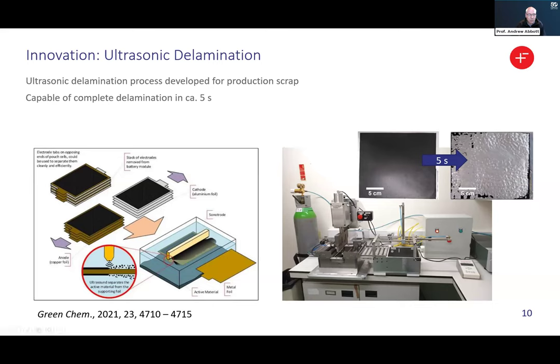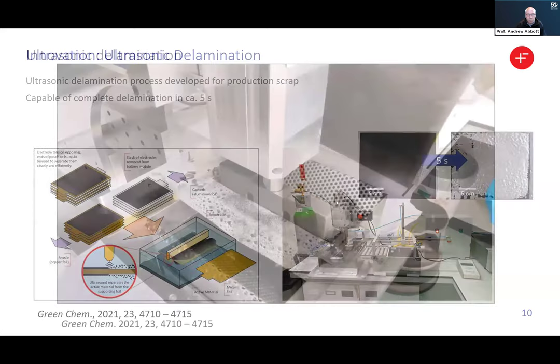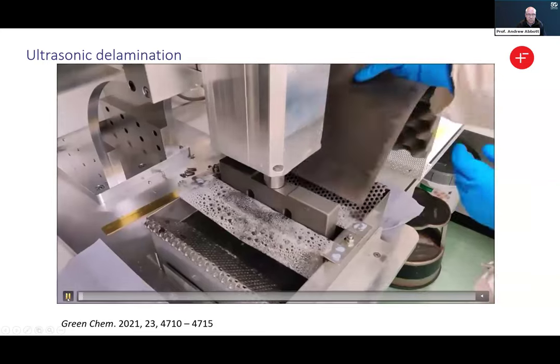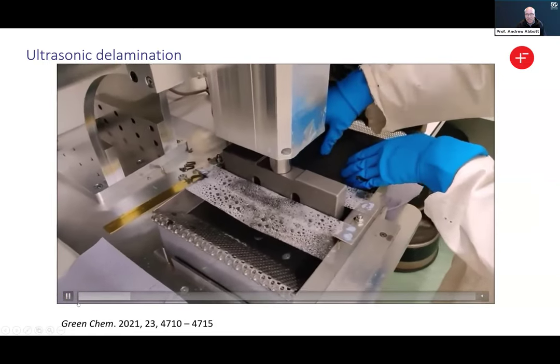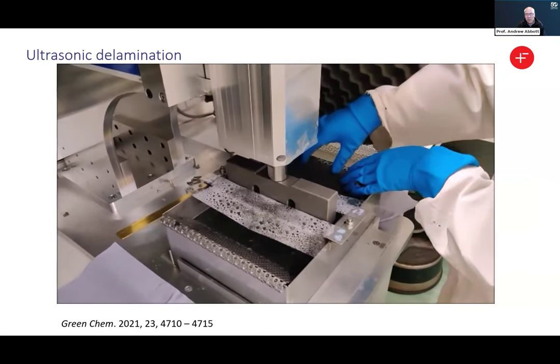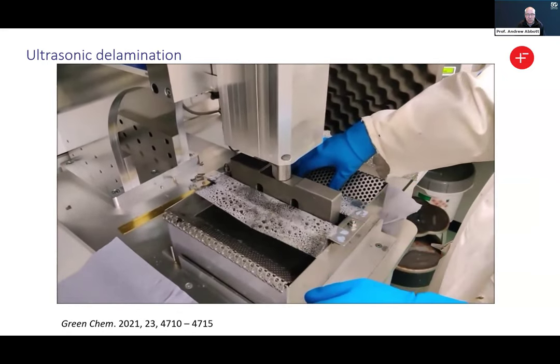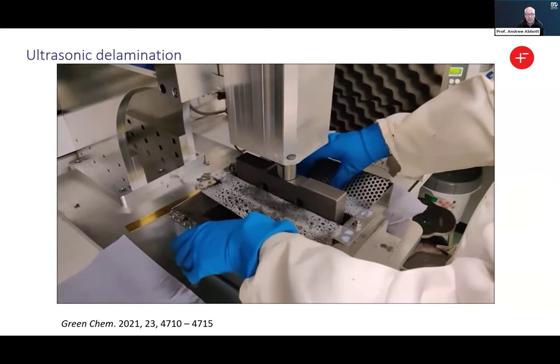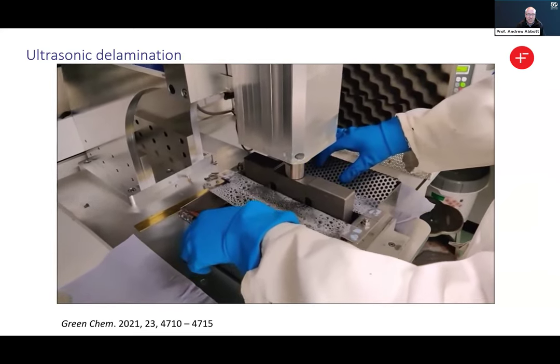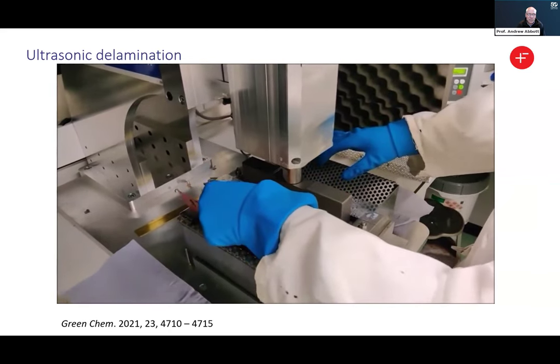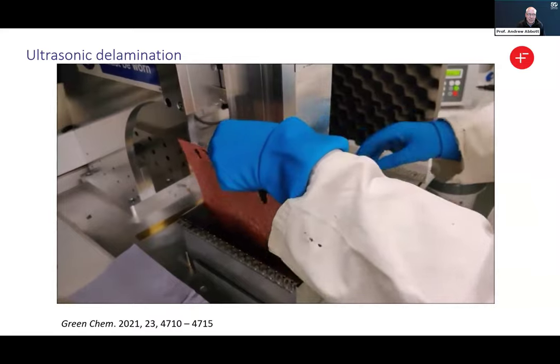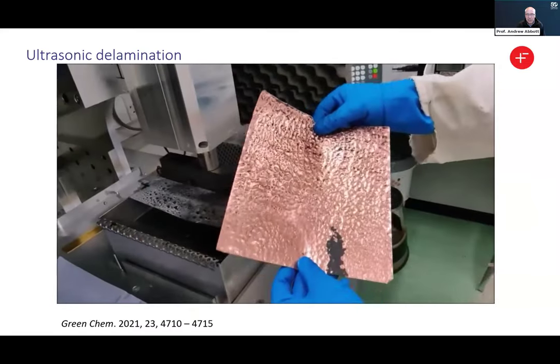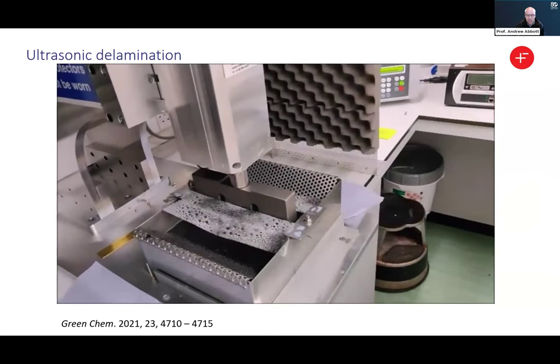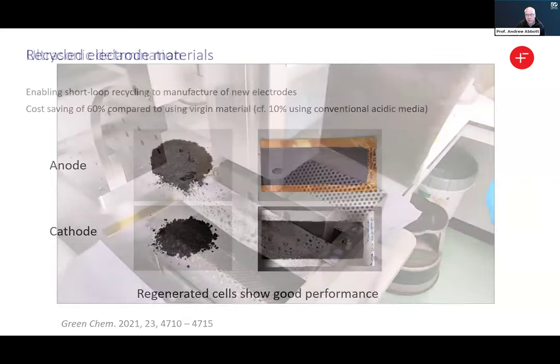So a very simple process, which is akin to the sort of process that you get when you go to the dentist and have your teeth cleaned. So just to give you an idea for this, this shows the sort of manual version of it. This is my postdoc Chun Hong, who's developed the process. And you can see that in a few seconds, it goes underneath the sonic horn, not heated up, not speeded up here. I've only done it on the anode here because it just gives you very clear visual context of it. The electrode is delaminated and separated in about 5 seconds. So you can see it's a very simple technology, low energy, and just uses water to be able to do that process.